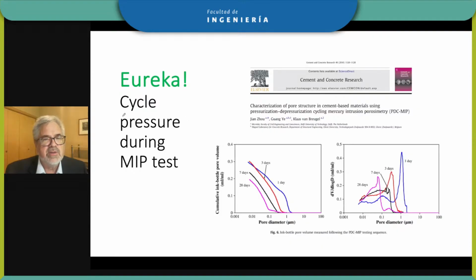And this, of course, was used by other researchers. This is an example where some researchers at Delft used our approach to do both the pressurizing and depressurizing and measuring volumes so that we could see the progressive refinement of pore structure with age. At 1 day, 3 days, 7 days, 28 days, the size of the pores gets smaller and smaller, validating our general understanding of cement hydration, how it densifies the microstructure.